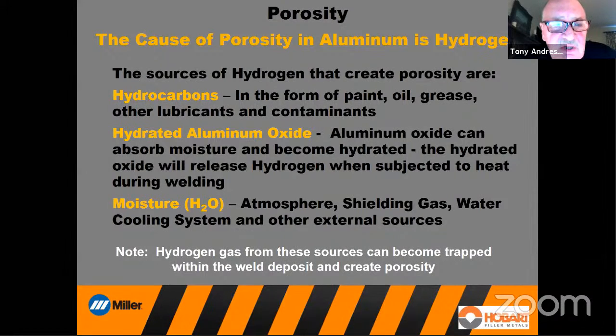So it can come from, I've listed 3 areas here of concern, and these are the typical 3 areas that you need to look at. Hydrocarbons is the first one. So that's any form of contamination, usually on the surface of the plate, but can be on the surface of the wire, right? Like oil, grease, paint, or any type of contaminant that might be on the surface that may have hydrocarbons in it can cause porosity.